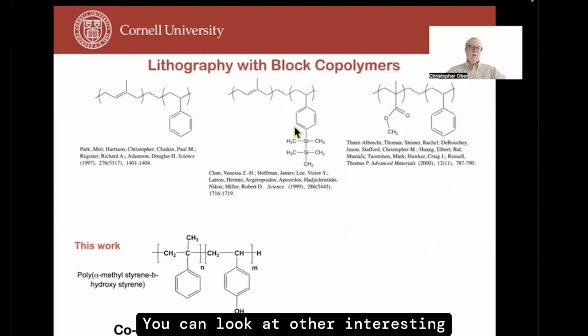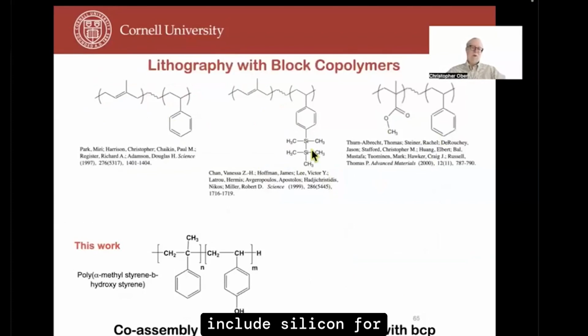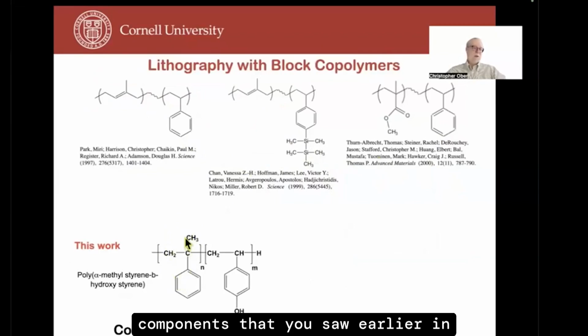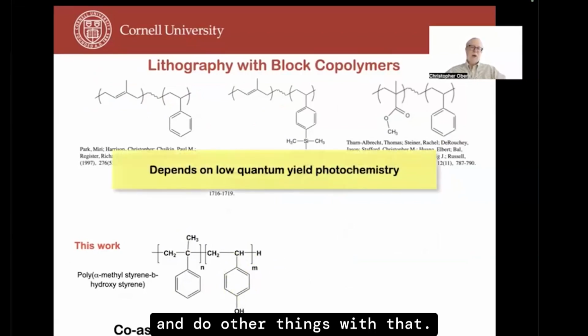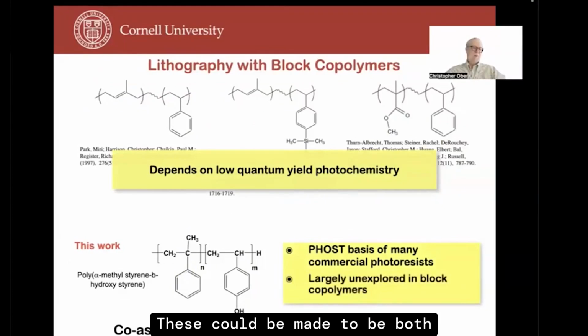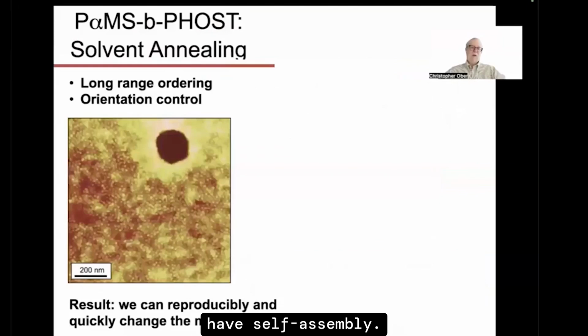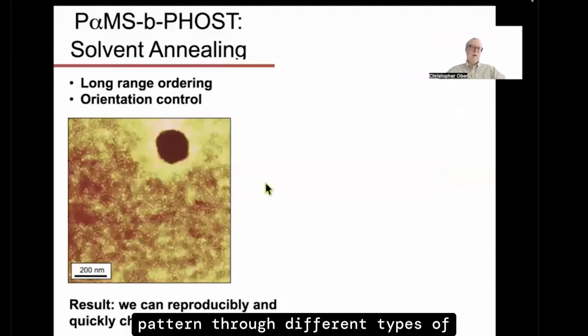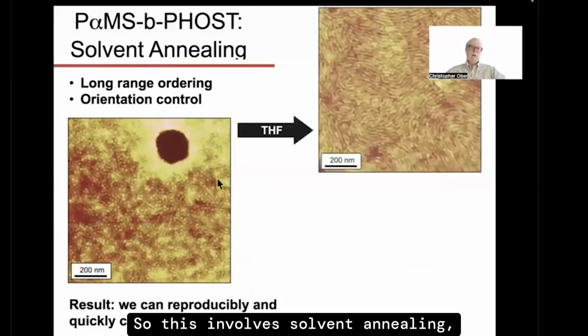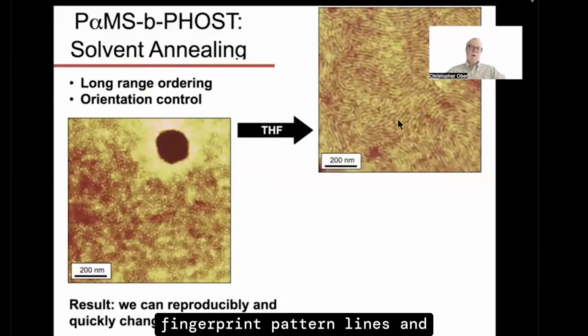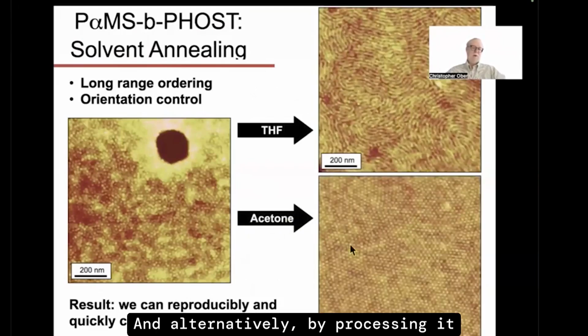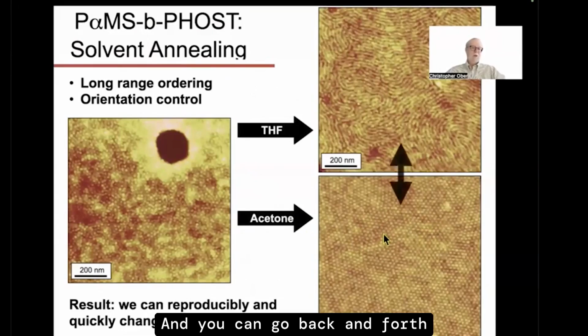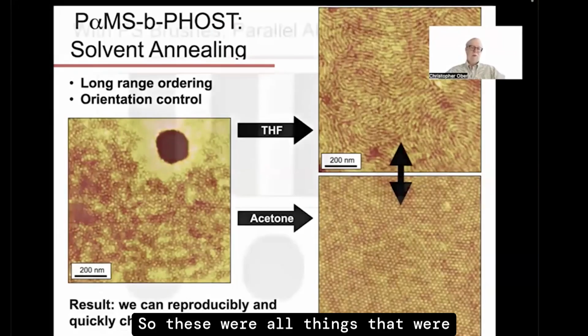You can look at other interesting structures that have been built, include silicon for phase contrast. You can also incorporate components that you saw earlier in the fast e-beam resist or in the early chemically amplified resist and do other things with that. So these guys are self-assembly. They don't interact with light. These could be made to be both patternable by light as well as have self-assembly. And you can change the kind of pattern through different types of processing. So this involves solvent annealing, where you can make a so-called fingerprint pattern, lines and spaces, and alternatively, by processing it differently, the same resist, you can make a series of dots, and you can go back and forth between them.